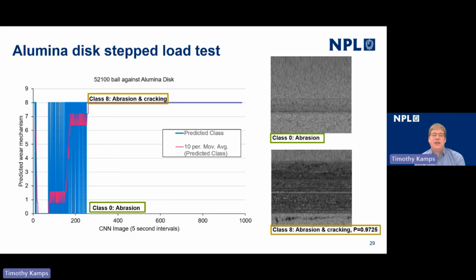And in the condition that this analysis was run in, what we were looking at was free running the acquisition around the disk and seeing what the probability was that we had abrasion on the disk surface or abrasion and cracking. And you can see after the test initially started off being classified as abrasion, the probability that we saw abrasion and cracking on the disk increased from the interval 50 through to interval 250 until the whole disk was covered in abrasion and cracking. And this gives us a way of capturing the transition from just abrasion to abrasion and cracking, but also looking at how that damage propagates around the wear track.